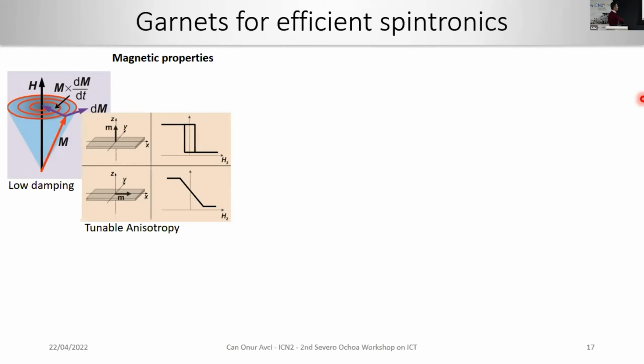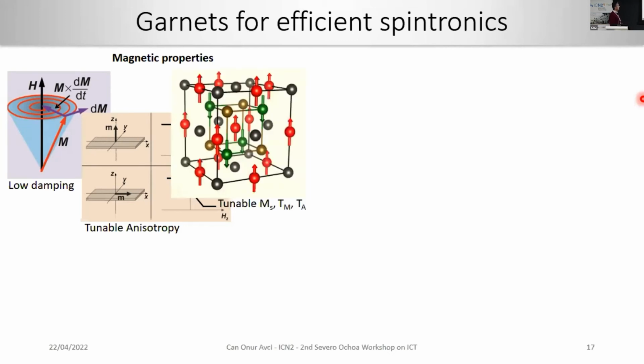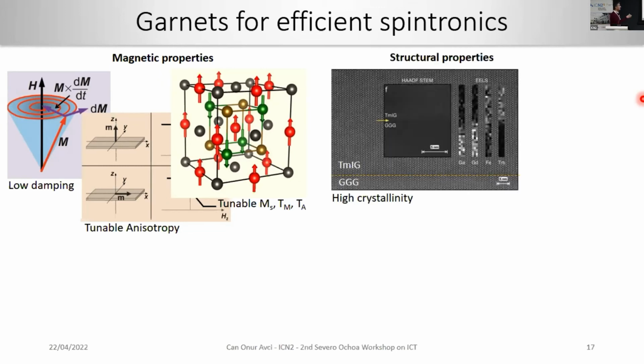Then it also has tunable anisotropy. You can have them in plane anisotropy or out of plane anisotropy, and anisotropy doesn't depend on the interfaces. Mostly in the case of conducting materials, it depends on the interfaces, but this is a bulk effect, so you can have it out of plane and have flexibility over the thickness of the material that you can grow. Then you have also tunable saturation magnetization, tunable magnetic compensation, tunable angular momentum compensation. That would be also useful for ultra-fast magnetization dynamics. On the structural side, you have very high crystallinity. You have single crystal epitaxial growth of, for example, in this case, thulium iron garnet on GGG substrates.